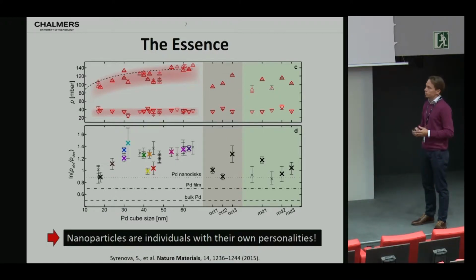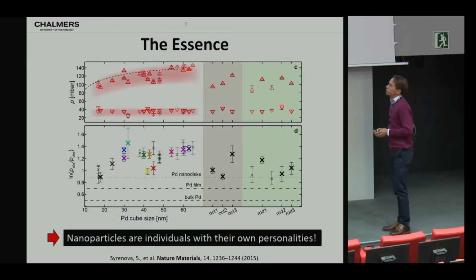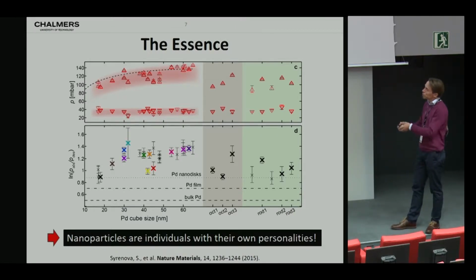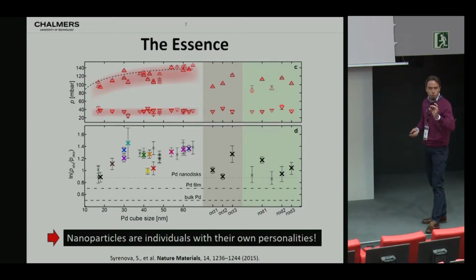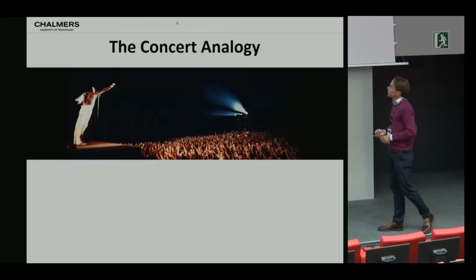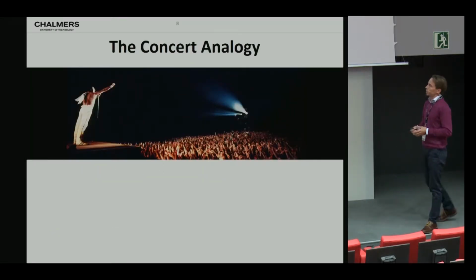Now you can ask, why is that? We believe it's related to the defect structure in the nanoparticle, but what I'm trying to say is that you would not find that if you would not look at them one at a time, because then what you would see is what is illustrated here by the shaded red area, which basically is the error bar from the corresponding ensemble measurement. So indeed, you can see beyond error bars, and you will find that nanoparticles are individuals with their own personalities. And we can explain this with a concert analogy.